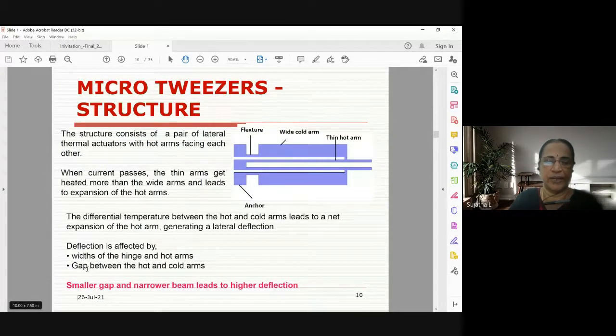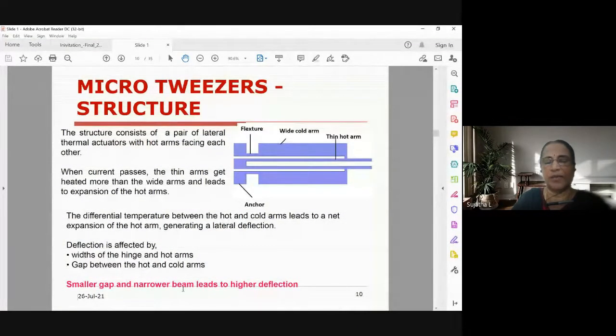The connecting point is given as the gap between hot and cold arms, and this will be the hinge width. What is the width here? So if there is more width on the flexure part, what will happen? The movement of this deflection may be reduced. That is, it will increase the stiffness and the deflection will decrease. With a smaller gap and narrower beam, if you keep a narrow, very thin beam, as well as a smaller gap between the hot and cold arm, we can produce very high deflection.